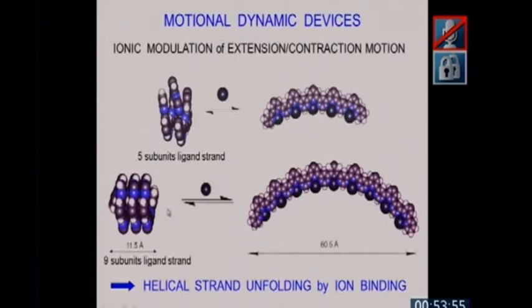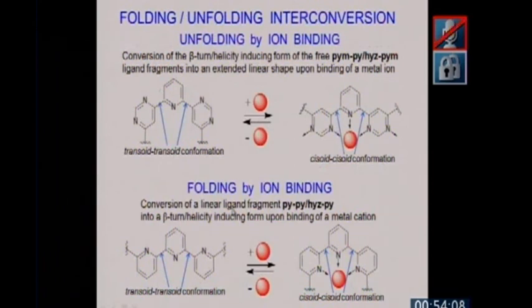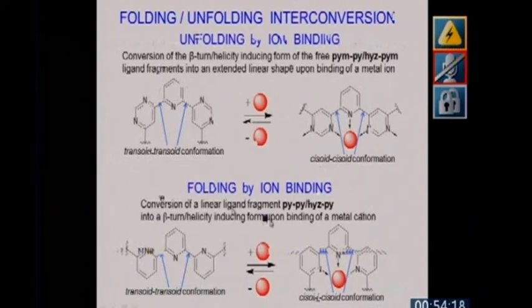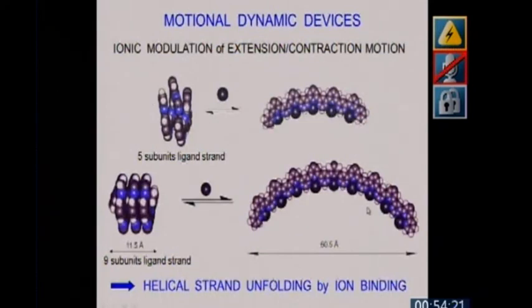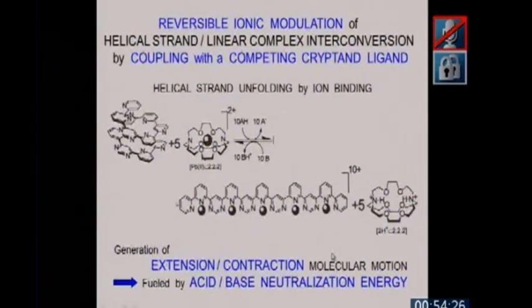This is the molecular model of one of those helices. It's about 11 angstroms long. And when you add lead ions, they bind to these subunits, to these sites here, as shown here. The leads are bound to these sites and extend the molecule. So you have an unfolding by ion binding. An interesting process you can then imagine is to try to reversibly modulate extension and contraction.